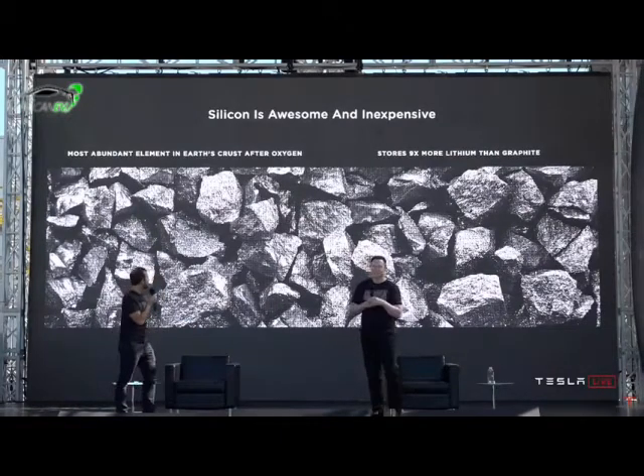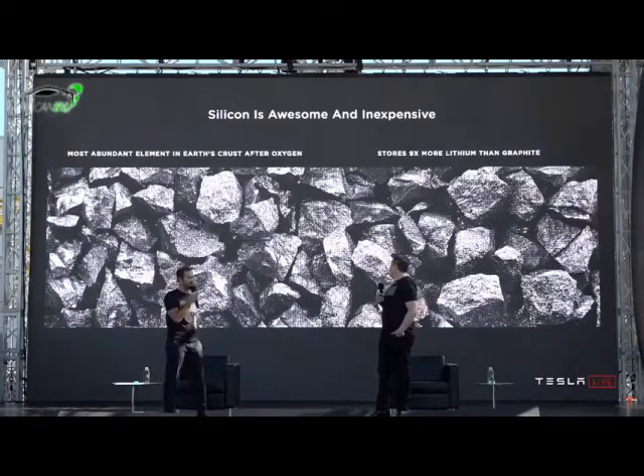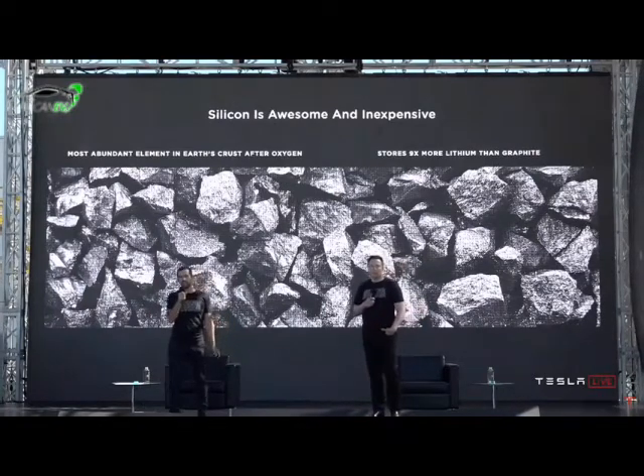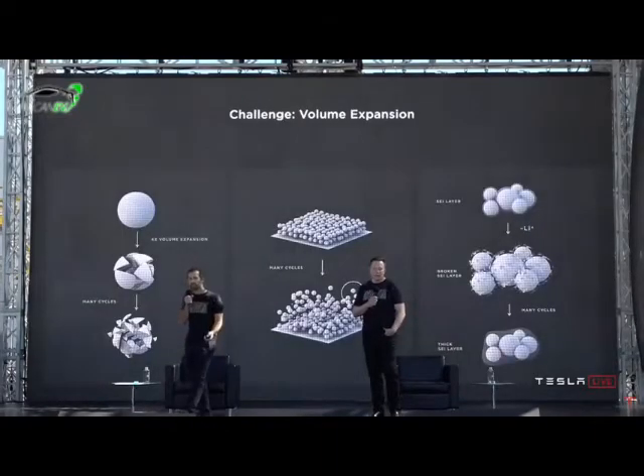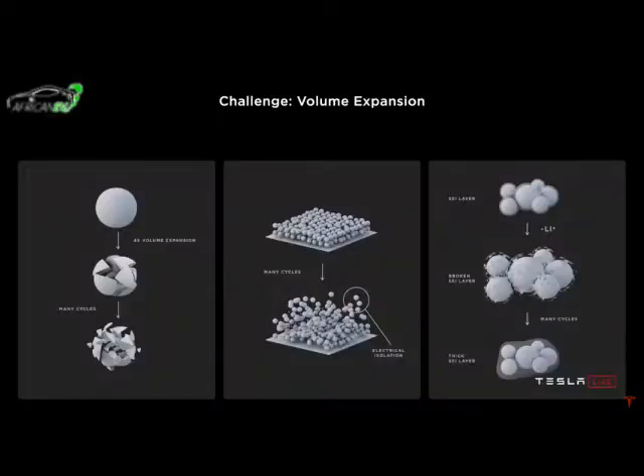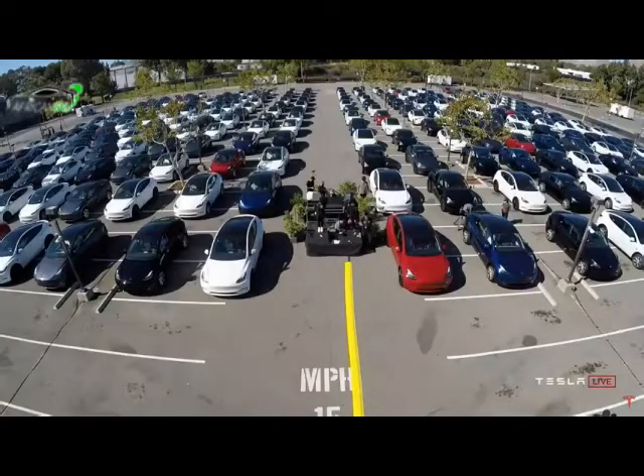And it happens to store 9 times more lithium than graphite, which is the typical anode material in lithium-ion batteries today. So why isn't everybody using it? The main reason is that the challenge with silicon is that it expands 4x when fully charged with lithium. And basically, all of that expansion stress on the particles starts cracking them, they start electrically isolating, you lose capacity, the energy retention of the battery starts to fade, and it also gums up with a passivation layer that has to keep reforming as the particles expand. Basically, with silicon, the cookie crumbles and gets gooey. That's basically what happens. Good analogy.